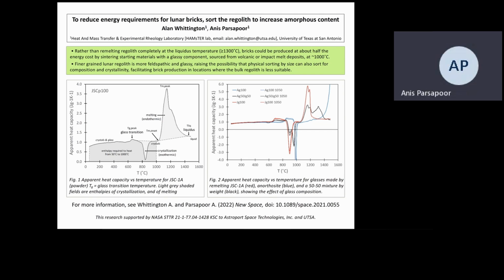As a powder, the enthalpy required to go from 50 degrees to complete melting is 1775 joules per gram for JSC-1 and about 1900 joules per gram for a 50-50 mixture by weight of JSC-1 and anorthosite. On the right side, the graphs represent remelted glass for JSC-1, Stillwater anorthosite, and the 50-50 mixture of JSC-1 and anorthosite. In this case, the total enthalpies required to achieve melting are systematically lower for glassy starting materials.